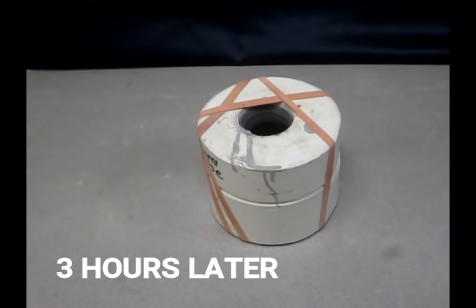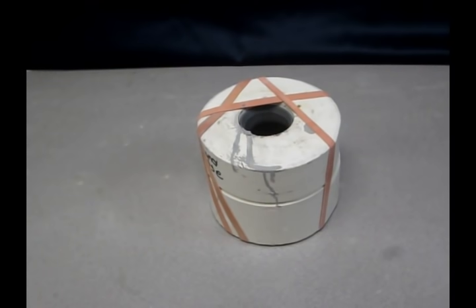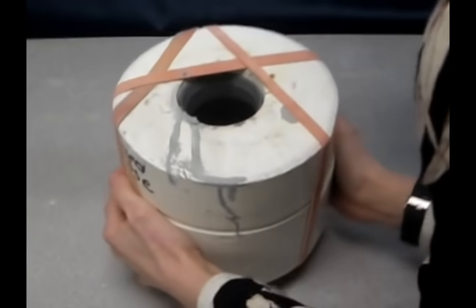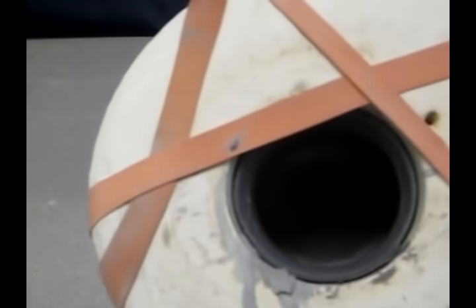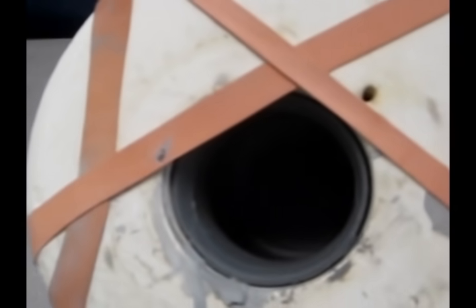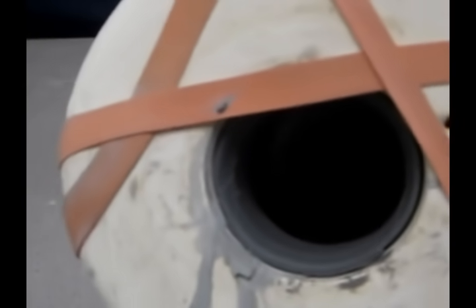It's been about three hours since I poured out the slip from the center of this slip cast mold. And you can see that the slip has solidified along the interior edges of my mold. And you may be able to tell on the camera there's a little bit of a gap between that clay and the mold because the moisture has evaporated and the clay has shrunk. So the clay is pulling away from the mold and that's important before we peel this apart.